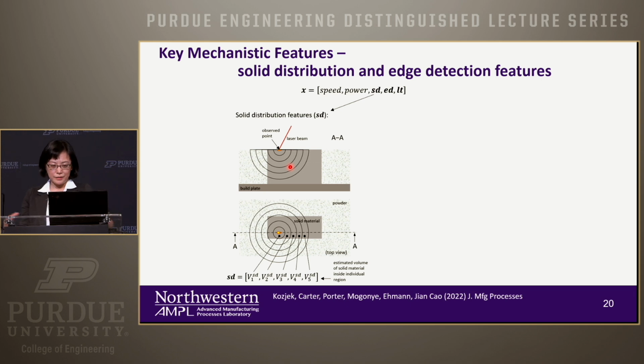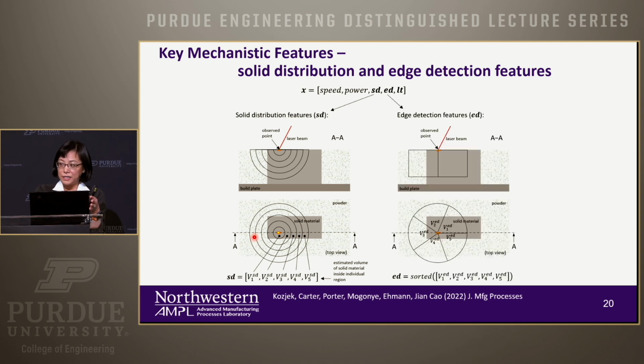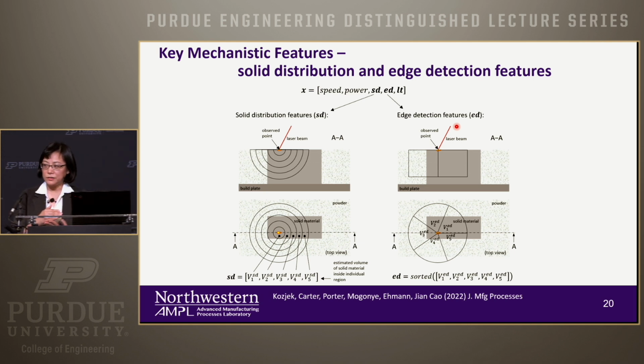You have multiple of these rings, actually multiple of these hemispheres. And by doing that, it's a vector, right? Here you have a vector of this SD, which gives you an idea what is the solid area surrounding this point. Similarly, as I mentioned, the edge versus the middle is also different, so you can also get the edge features by doing this geometric analysis. All of these features, you can compute offline. Once you have the part, you can analyze it, right? And therefore you have these mechanistic features, and then we train on a couple of those runs, and then you can use that for prediction.